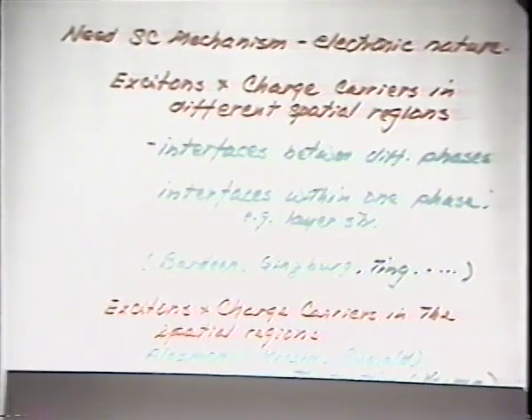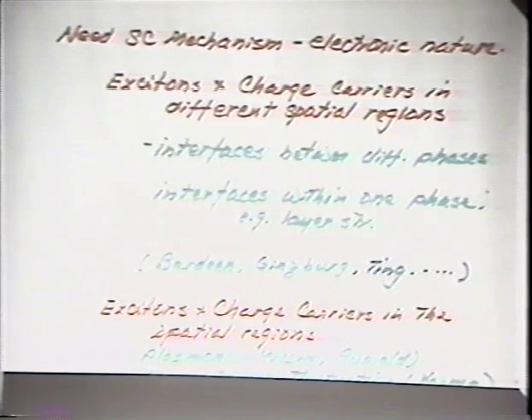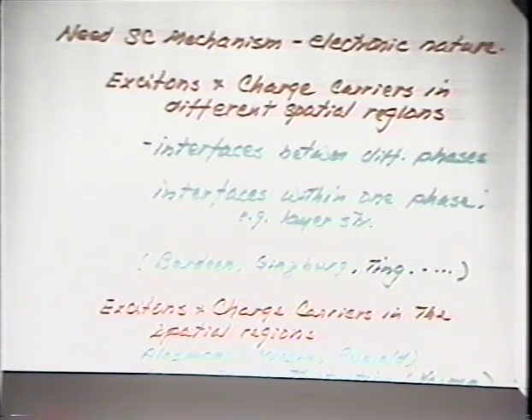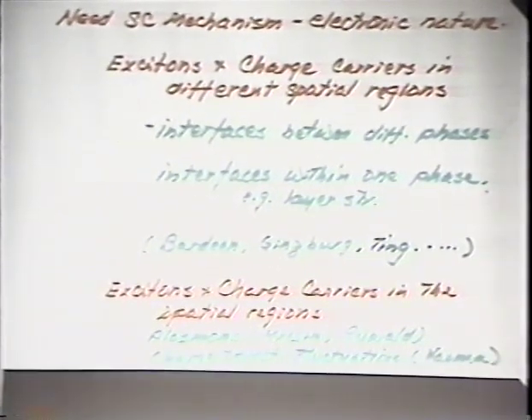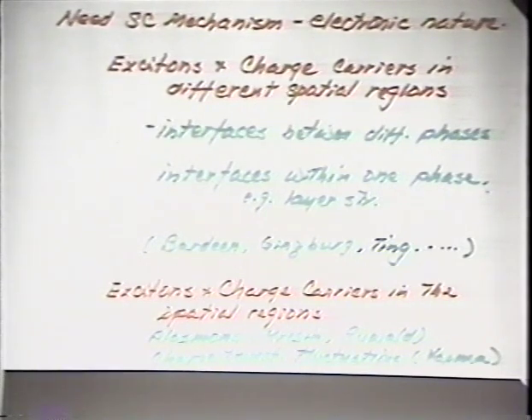Now, what would happen in the other case, where the excitons and charge carriers are in the same spatial regions? Okay? In that case, we can make use of the so-called plasmon mechanism, which has been proposed by Chakravarty of Lawrence Berkeley Lab, LBL, and also John Ruvalds of the University of Virginia. According to their models, 2-dimensional plasmons, acoustic plasmons, can help us to achieve higher TC. But then what about the charge? Because when you look into this layer, the copper charges are transferring between different states, and therefore Chandra Varma proposed a charge transfer fluctuation situation where you can get an enhancement in superconducting interaction.